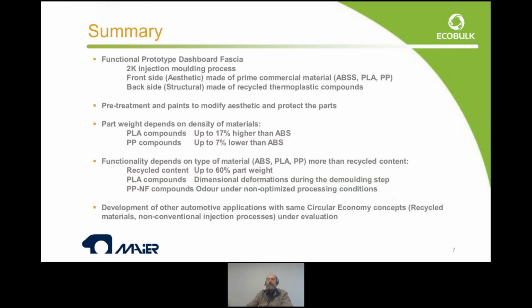And if we go ahead, I would like to summarize that the most important result we got from this demonstrator, from this prototype version of the dashboard fascia, is that yes, of course, it's possible to produce a 2K component fully functional with, at the same time, mechanical and thermal behavior and good aesthetics, and obviously the part weight depends not on the amount of recycled content, but on the kind of thermoplastic compound you use to produce it.